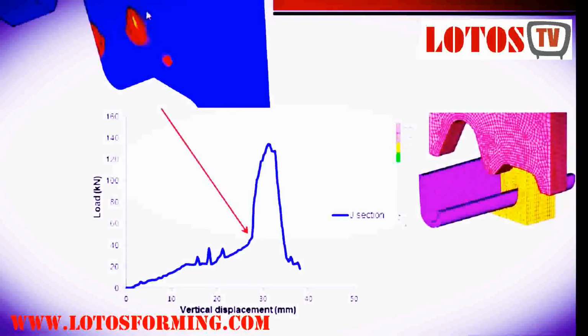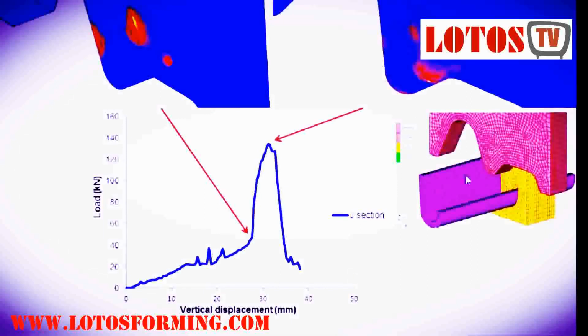to be cut. So you can see back on this photo the very high stress developed in the plate at this position. This causes fracture and damage in the plate. When the plate goes down further to cut most of the material at the bottom of the J section, some further high stress develops at the bottom of the plate that causes fracture and damage in the plate.